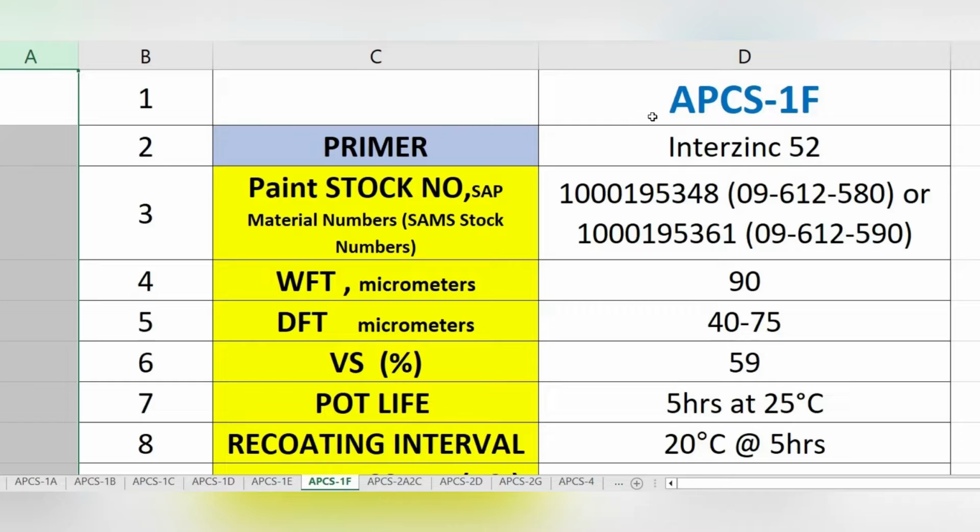Epoxy polyurethane coating system for atmospheric services with zinc-rich epoxy primer. Maintains painting for severe atmospheric exposure when added gloss retention, color retention and abrasion resistance are required, usually outdoors. Maximum service temperature 80 degrees Celsius.